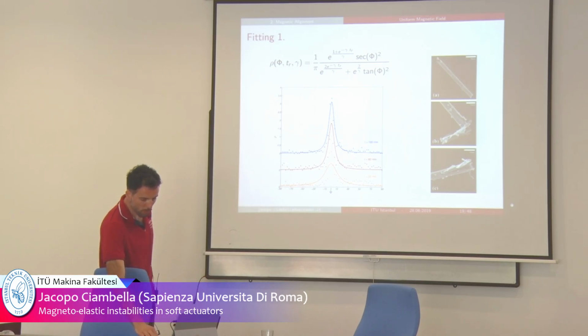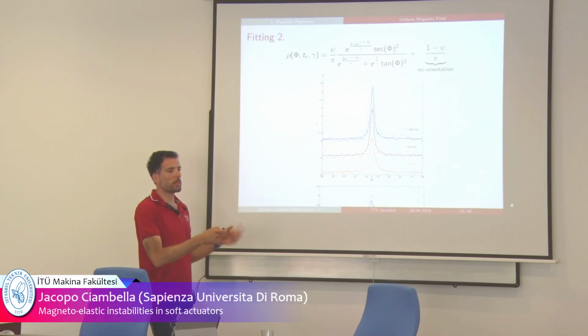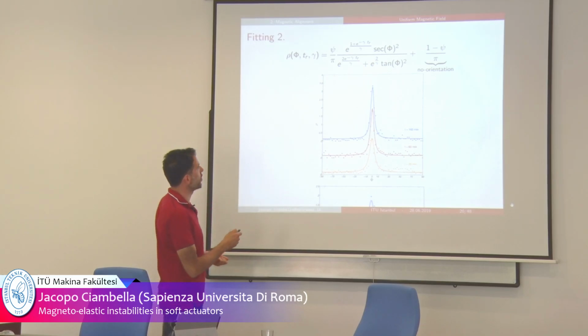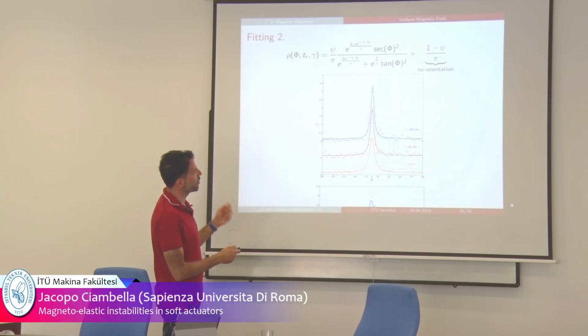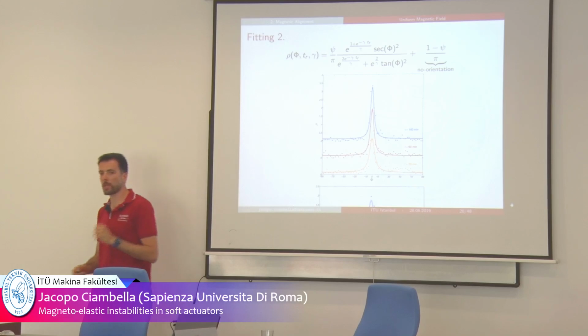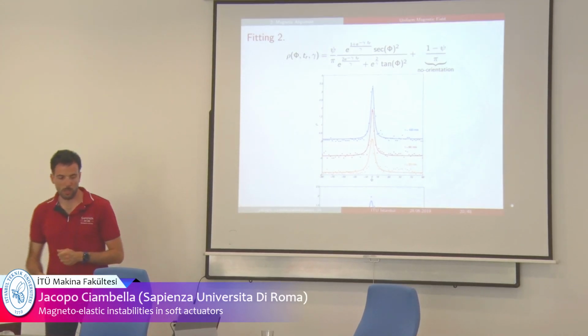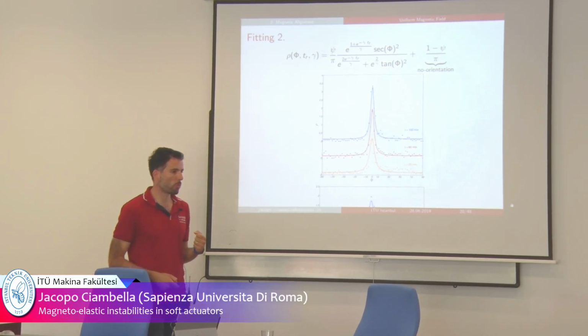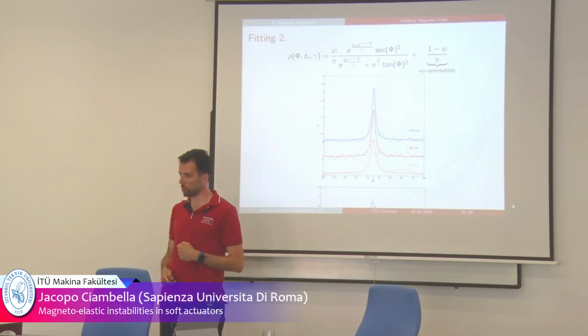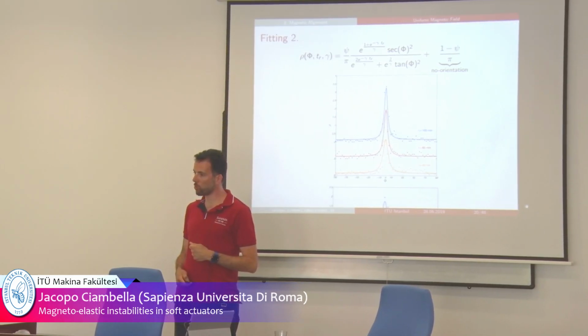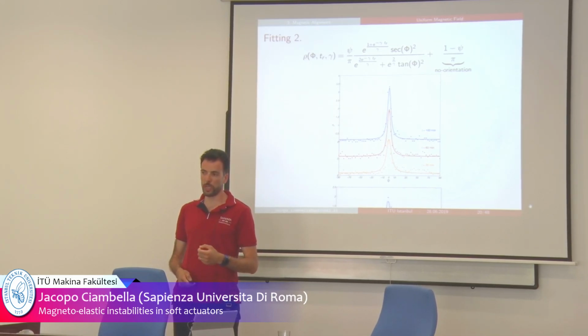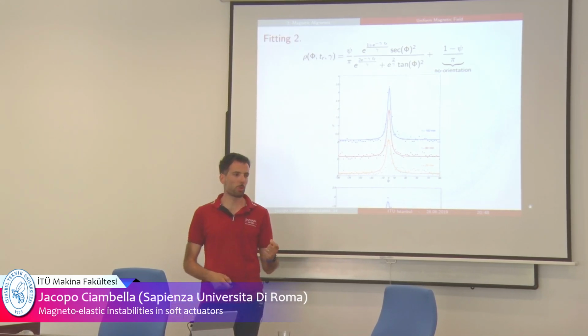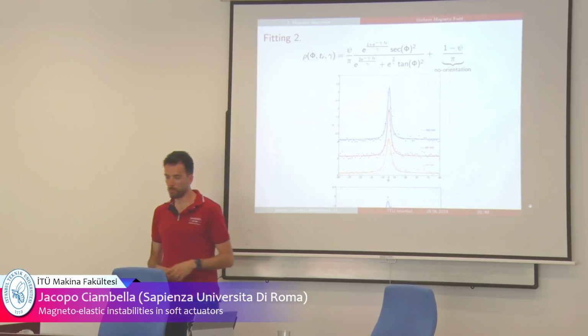And in fact, if you modify this equation by adding a certain rule of mixture, so you imagine having a certain percentage of fiber which are able to orient themselves and a certain percentage of fiber where no orientation occurs, you get a much better fitting. Okay? And so this suggests that we had to improve our manufacturing methodology. One of the ways we used to disperse fibers inside the PDMS was sonication. And probably sonication was not good for the coating.